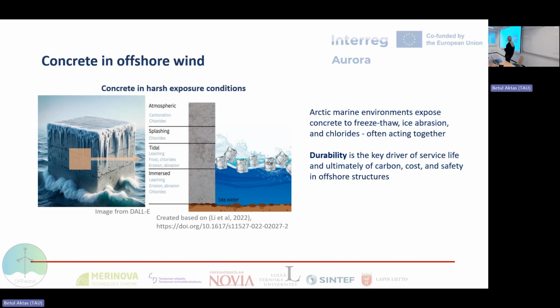So here in this picture, you can see what concrete has to endure when it is placed in an environment like Arctic offshore structures. So it is subjected to several different actions from the seawater, from the atmosphere, the freeze and thaw cycles, and also the ice abrasion. So if we consider those difficult conditions that it has to act in, then durability of this material is one of the main parameters. So usually for those who work with concrete, we talk about strength a lot, but durability is a key factor, especially in conditions like this.